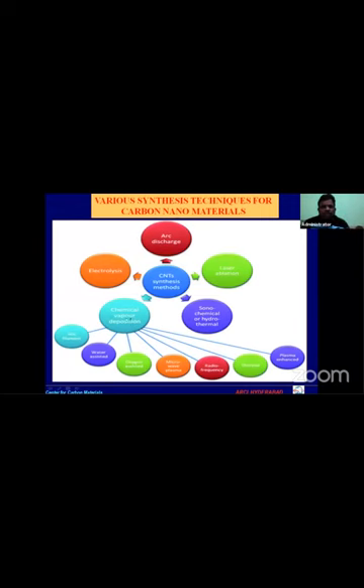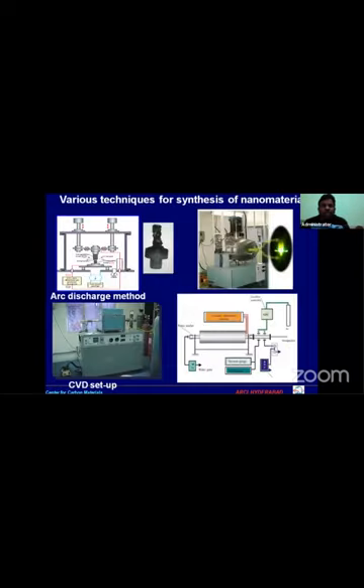Many things are there. We have in our center the arc discharge, where two graphite electrodes are taken and a very high current is passed, and you will get a deposit. This is called a cathode deposit, and in this deposit a lot of nanotubes will be there. In the CVD reactor, the carbon nanotubes grow in different types of alignment. You can control it, like vertically aligned carbon nanotubes can be developed in this reactor.